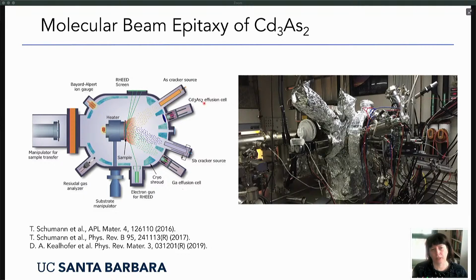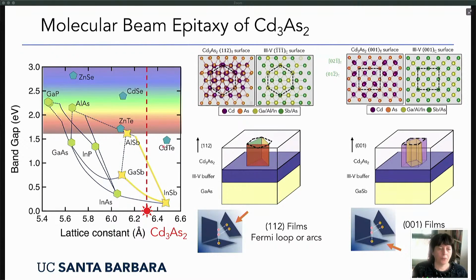It turns out the growth of cadmium arsenide is relatively straightforward, but there are other problems, and they are related to the substrates. Cadmium arsenide, as I mentioned, has a very large unit cell, and the pseudo-cubic lattice parameter is very large compared to the substrates and buffer layers that we are using, which are these 3-5 semiconductors. So here's cadmium arsenide.